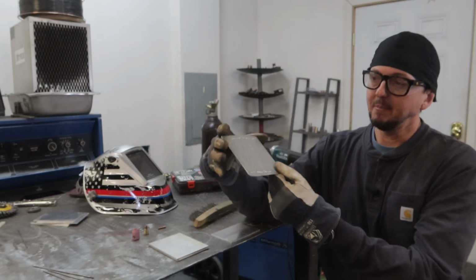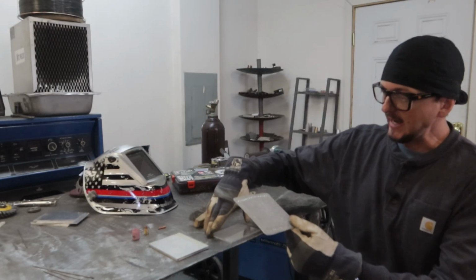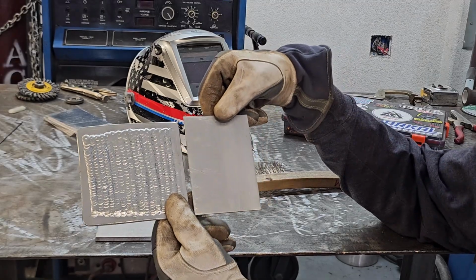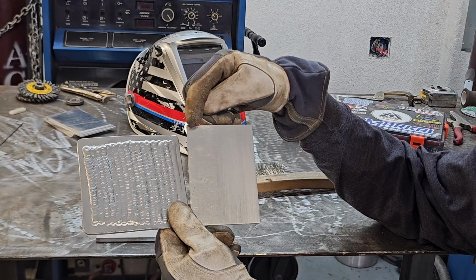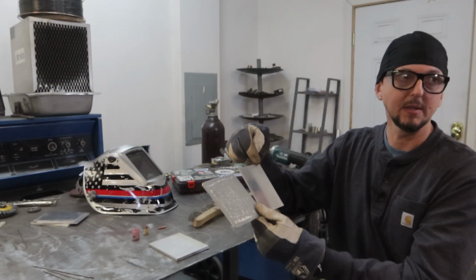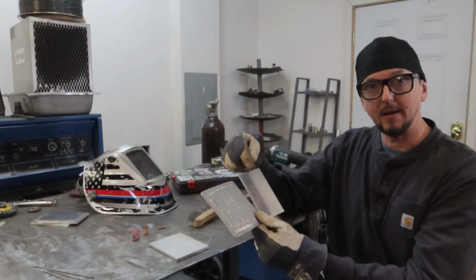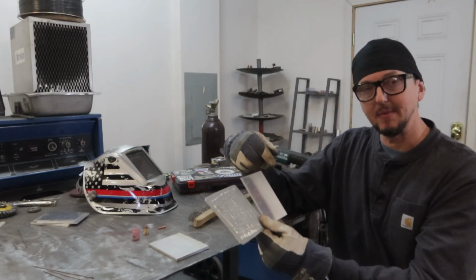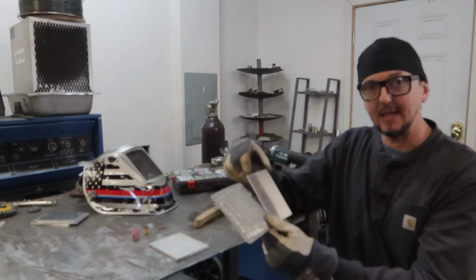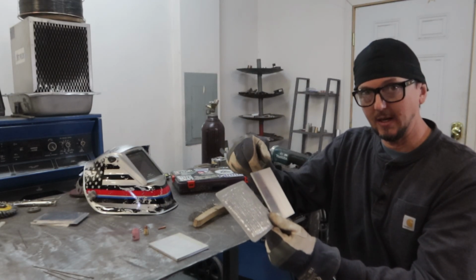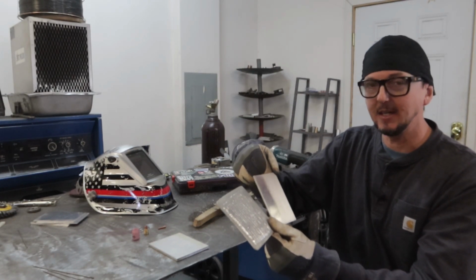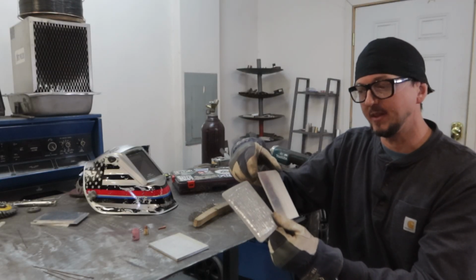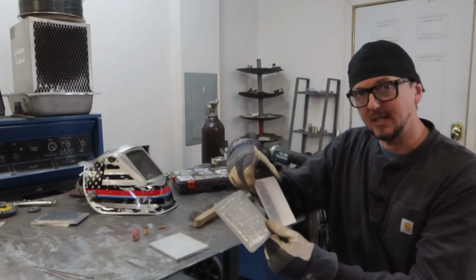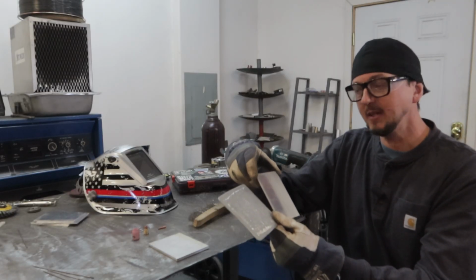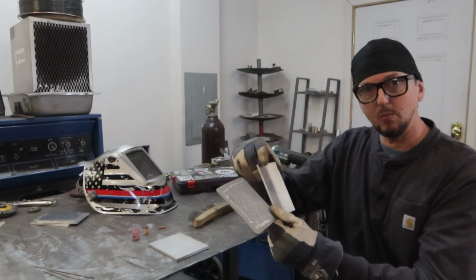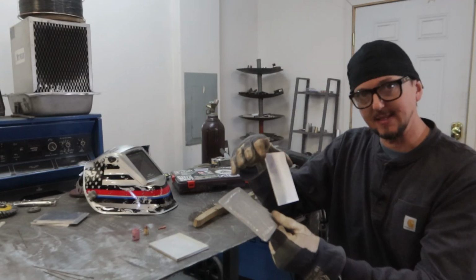Okay, so we're going to pick one direction. If we have a piece that's like this, most likely where we want to start is going this direction, because that will shorten our overall amount of welding time, amount of arc time, which means that we'll get less heat input with each weld, which will help you to control your heat input a little bit with this project. You're going to see that over time, you're going to need to give it time to cool down. You might get about 3 welds in before you need to let it sit and cool down.